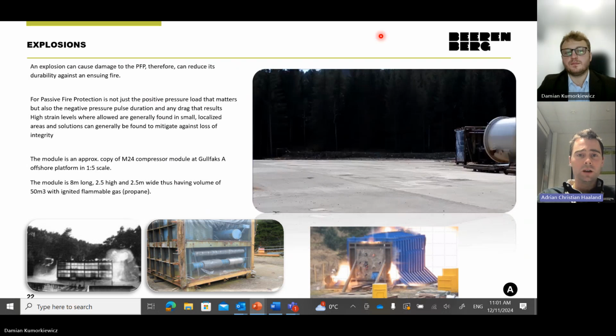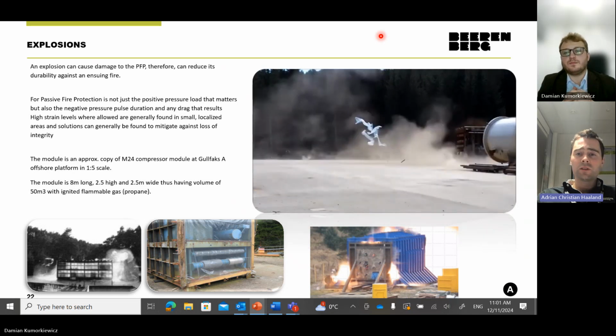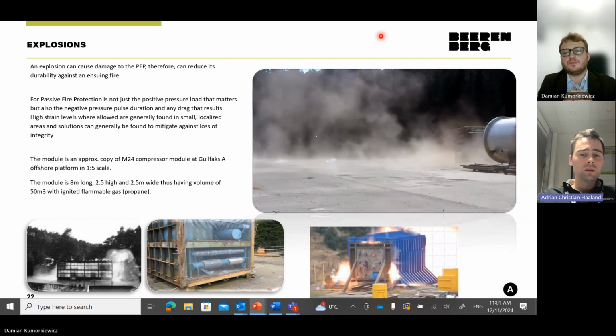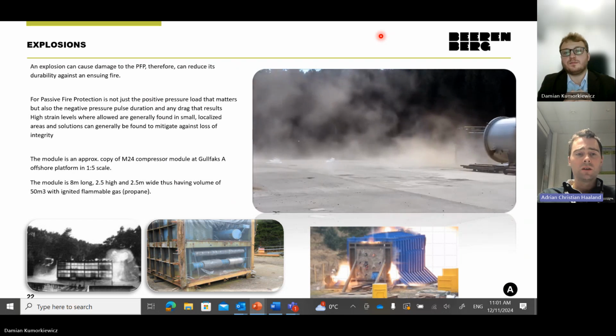Here is a brief snapshot of an explosion test. This was an open module to capture the effects of drag forces as well. And you will see on the video soon to be shown here that we have test specimens fixed on the end of the container module, which you also see a picture of in the bottom center picture here. The intent of this type of testing is to verify that the product can actually retain integrity when being subjected to quite extreme explosion pressures generated from igniting gas sources in the process area. Typical pressures from this can range from 0.2, 0.3 up to 1.5 bar for a typical gas explosion scenario.